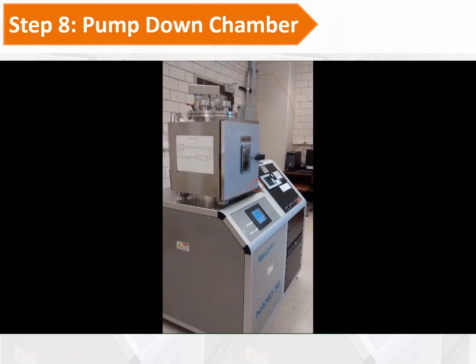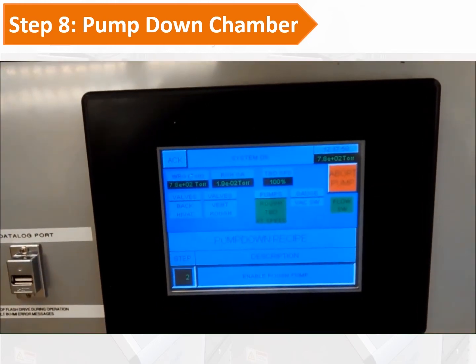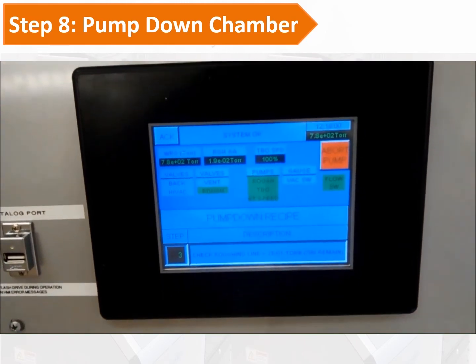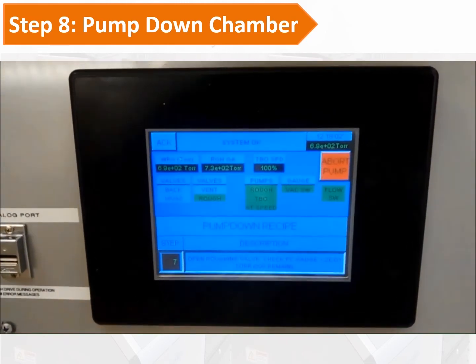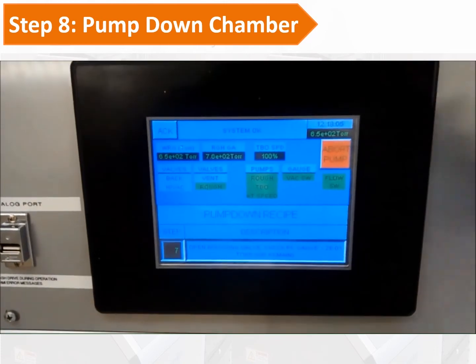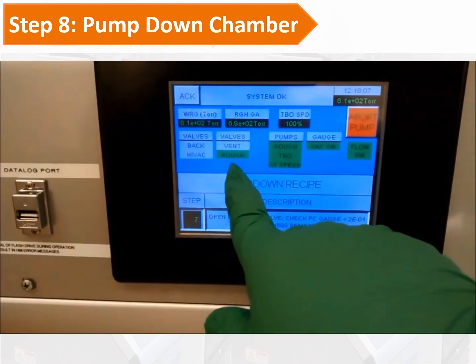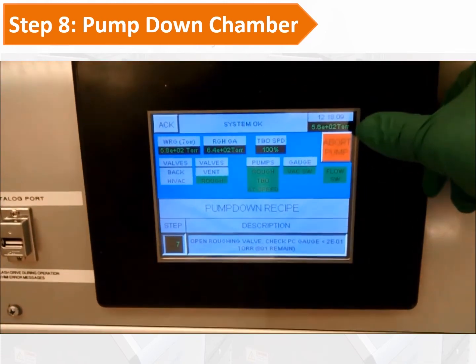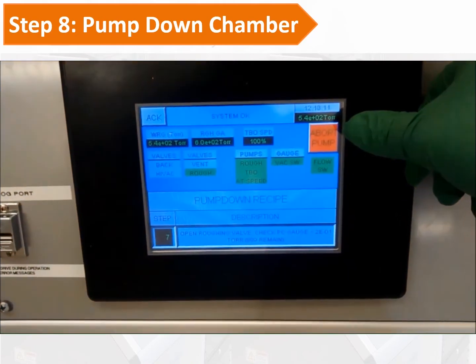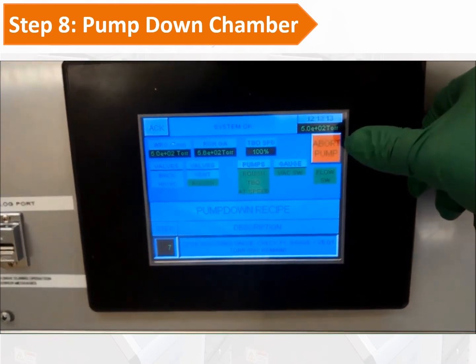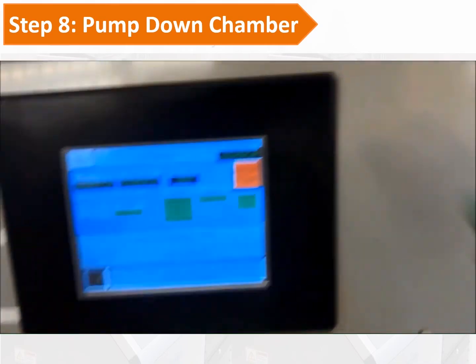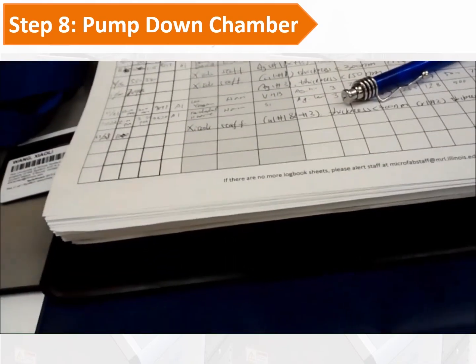You need to wait around 3 to 5 minutes and check whether the roughing valve is opening, and also check whether the pressure drops. If you find the pressure drops, then you can fill out your information in the paper logbook, and now you can leave the lab.